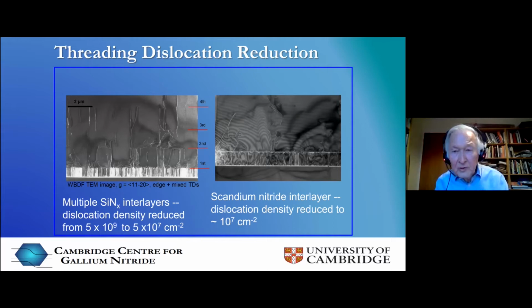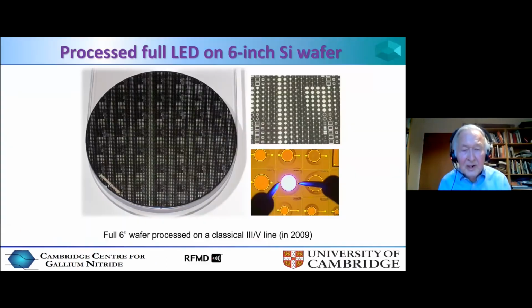And you can also reduce the dislocation density in another way by introducing a silicon nitride interlayer. But if we choose to do that, you have to take the specimen out of the growth reactor. And that costs money if you're trying to reduce costs. And so on the left-hand side, that's all done in the growth reactor without taking the specimen out. And so by that means, we've reduced the dislocation density by 2 orders of magnitude. And this enabled us then to grow gallium nitride LEDs on a 6-inch silicon wafer.